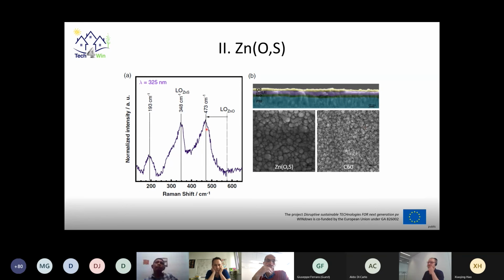So, material characteristics. Here you see some Raman spectroscopy measurements indicating that this peak at 193 is zinc oxysulfide, that we indeed have the mixed phase. Then you also see the zinc sulfide and the zinc oxide peak has been shifted to 473. And from that shift, we indeed can calculate the composition, and we see that the sulfur is around 0.6, so around 60% sulfur. So that makes all sense.